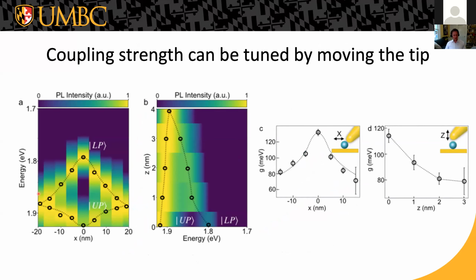And we can see why this happens, again, turning to finite element calculations. If you take the tip that's already sitting on top of the quantum dot and you move it away, then what's happening is just the cavity is getting bigger and bigger. The mode volume is getting larger, the coupling strength dies down, and that happens on dimensions comparable to the size of the mode volume of the cavity in the first place. So your coupling factor dies off in a couple of nanometers.